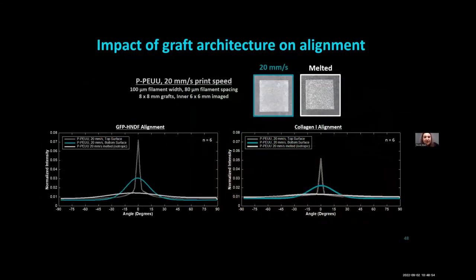And so this is an example of the plots that we end up getting for fibroblast alignment and collagen alignment, both on the top of these graphs, which you can see with the gray lines, a very sharp peak. So a lot of these cells are sitting in these little valleys between the filaments. But still on the bottom surface of the graft, we were able to get cell alignment, likely due to this mechanical anisotropy in the grafts themselves. Even when, interestingly, these grafts are melted, you see that this disappears, suggesting that something in the printing itself is actually guiding this cell alignment process.